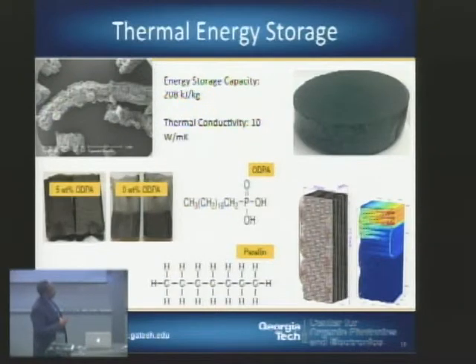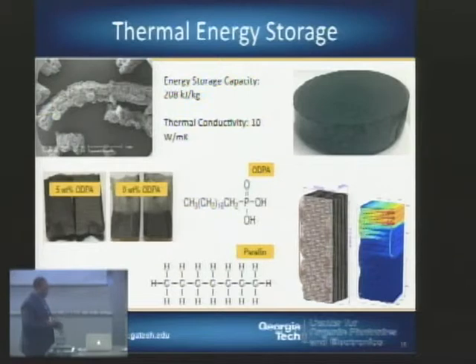so it takes a long time to thermally charge and thermally discharge. In this particular system, we can add something called compressed expanded natural graphite. So basically, this is a very simple system. You buy intercalated graphite film sheets, and you expand them using microwave energy, and then you use that like a sponge to soak up the paraffin wax.